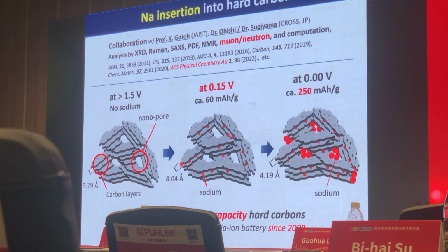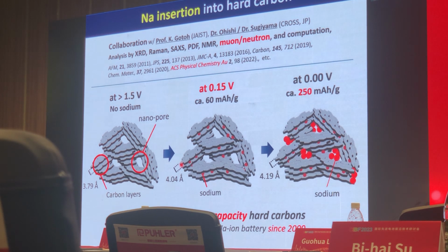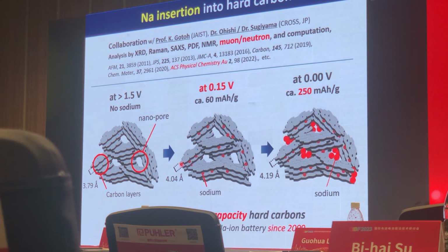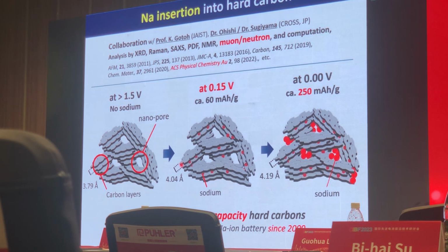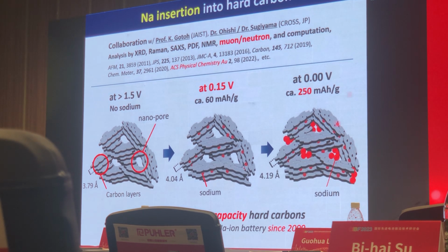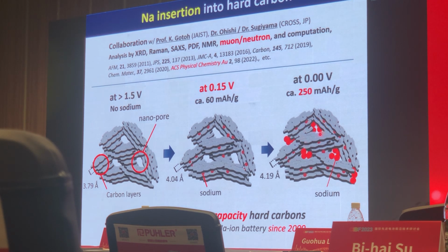Because of our successful development of long cycle life hard carbon, we are able to analyze the sodium insertion mechanism based on a highly reversible electrolyte system. In our collaboration with Professor Goto and Dr. Oishi, we understood that sodium is inserted into the interstitial layer spaces, then at the lower potential region, sodium cluster formation occurs in nanosized pores. Then we can demonstrate 250 mAh/g.